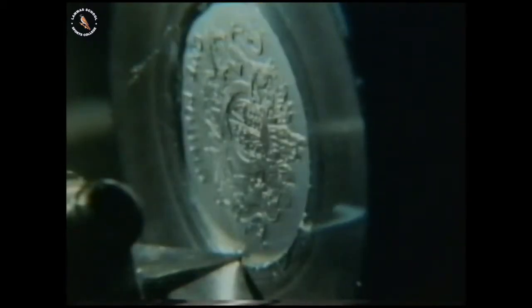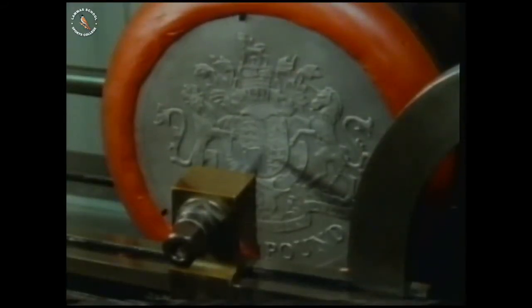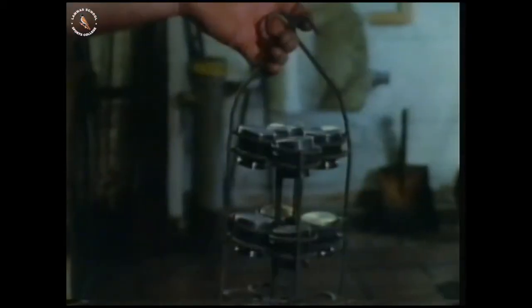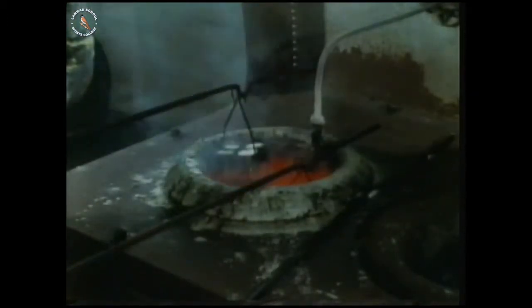Oil on the block helps to lubricate and cool. The first cut takes 12 to 14 hours. The final cut, 20 to 24 hours. But with special film, you can see it all happen in less than 30 seconds. In the soft steel block are all the details of the original design. But before it can be used as a punch, the soft steel has to be hardened by heating to 850 degrees Celsius for 50 minutes, cooling quickly to room temperature, then leaving in a salt bath at 180 degrees Celsius for an hour.